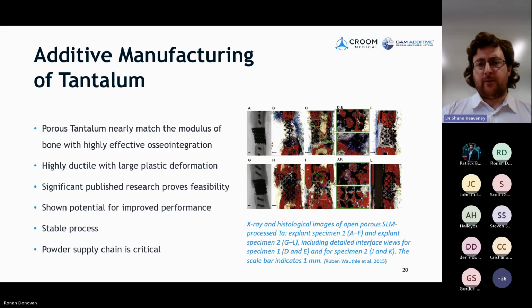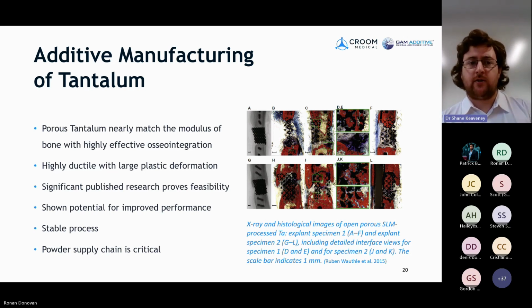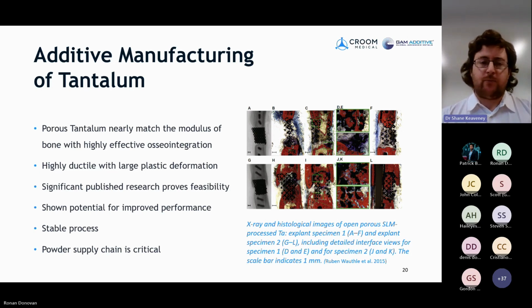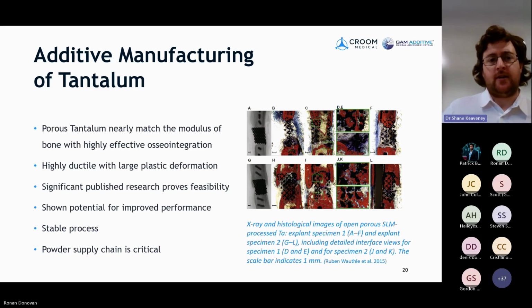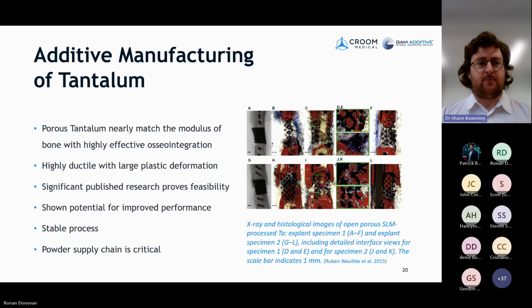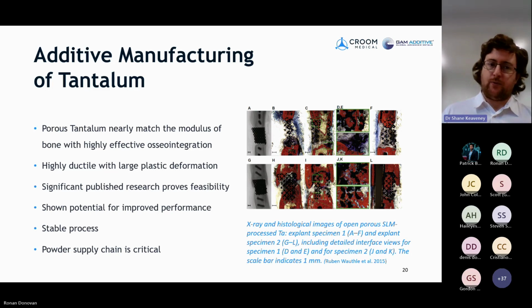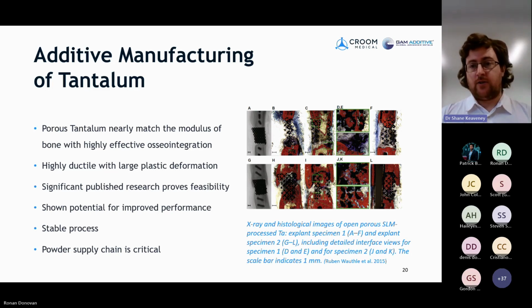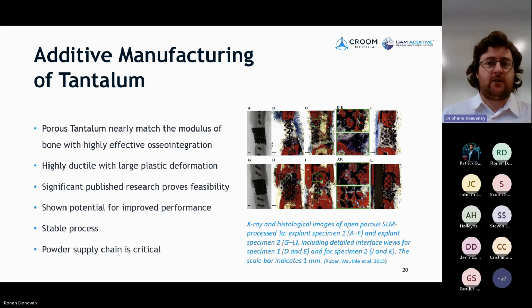So that's very beneficial if we have, say, larger implants or implants that are under cyclical loading or that may have some potential for strain to happen. There's less likelihood of a catastrophic failure. So like Gordon mentioned towards fatigue. So that's quite an interesting property, and I'll go through a little bit demonstrating that result in a bit. As I said, there's quite a significant amount of published research. So that's proved the feasibility, and it also has shown the improved performance from using tantalum. So we wanted to demonstrate that in a scaled up fashion in industrial settings.